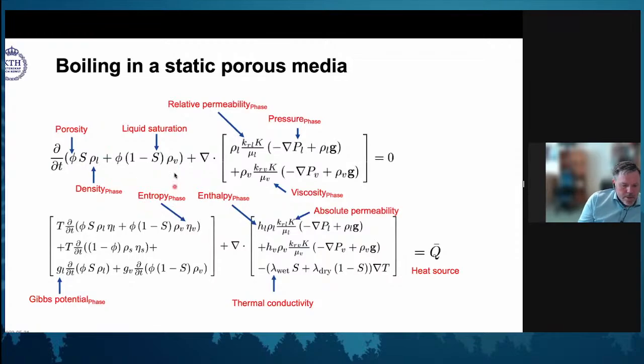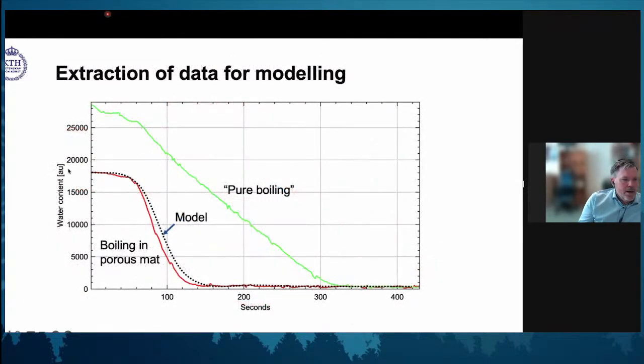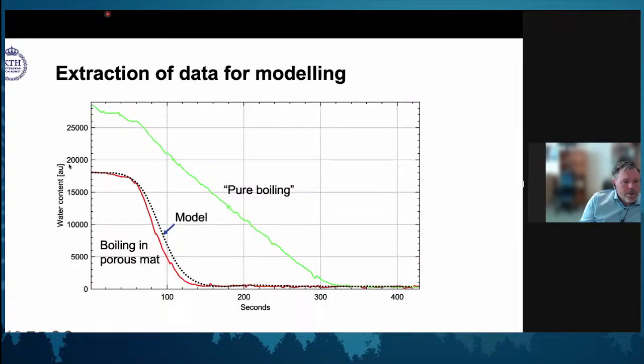If you take all of this, you can actually take the measurements that were done, very simple measurements. It's a 2D measurement, so that of course contains information on what happens because we have a shrinking blob in the center. But if you evaluate the drying of it, you can actually take the measurement and extract data for modeling. So when we have the measurement, we knew that the amount of neutrons that we detect is related to the amount of water we have. So by this, we can actually normalize it such that we can measure the exact amount of water and fit the model as depicted to what we have seen in the image.